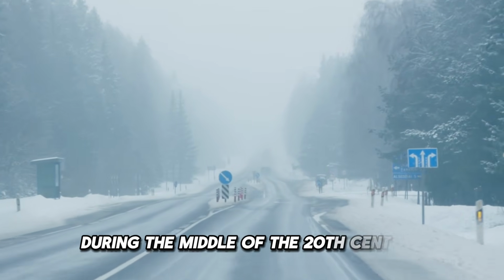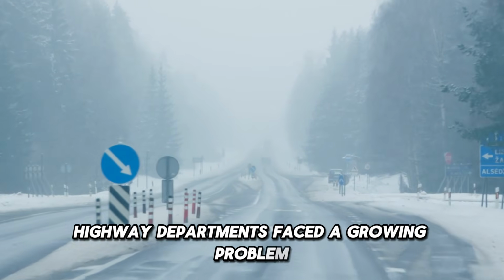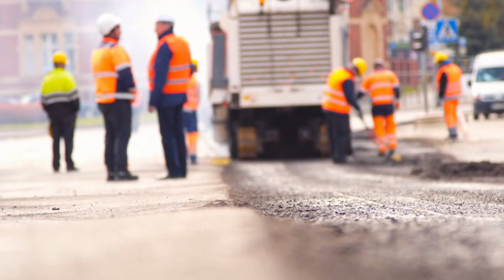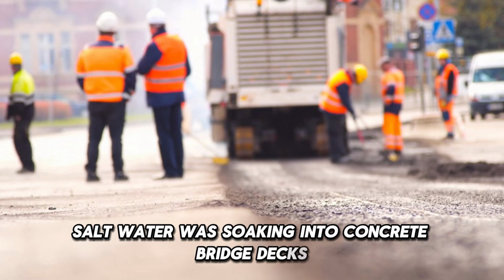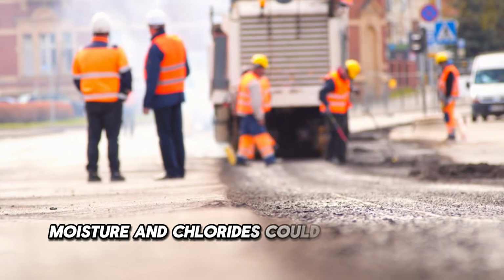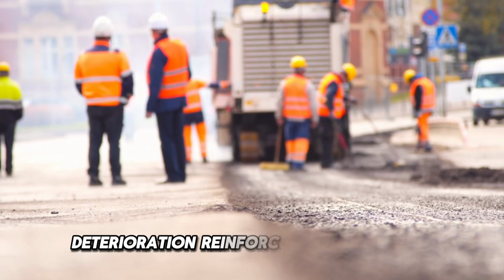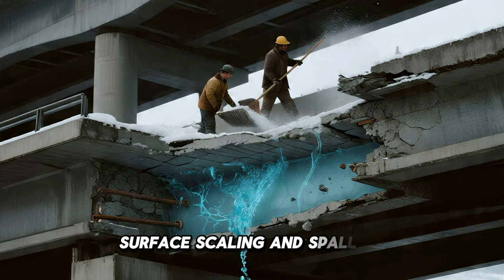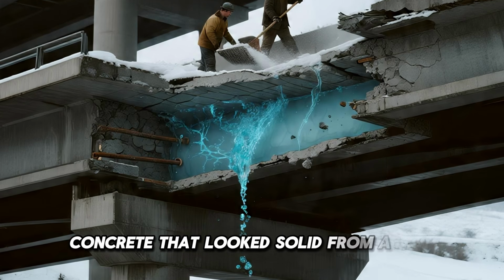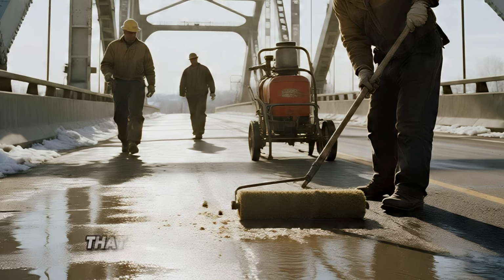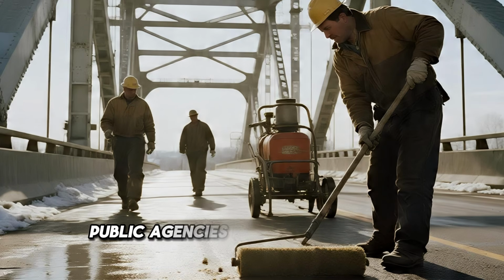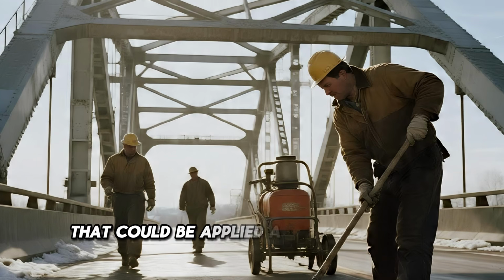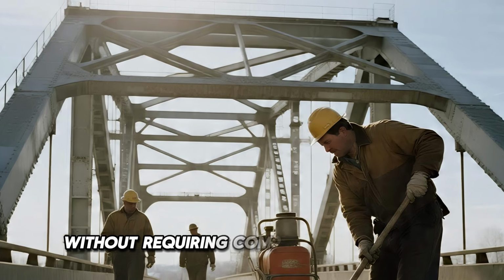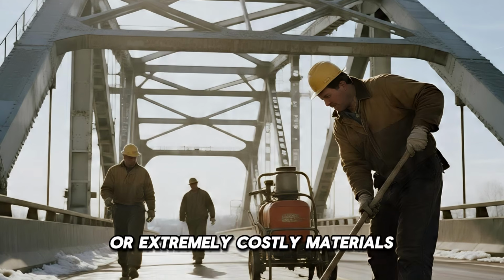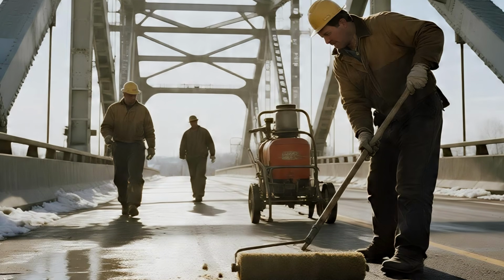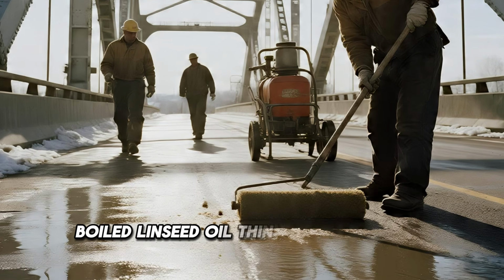During the middle of the 20th century, highway departments faced a growing problem as winter road salting became more common. Salt water was soaking into concrete bridge decks. Once inside, moisture and chlorides could contribute to freeze-thaw deterioration, reinforcement corrosion, surface scaling, and spalling. Concrete that looked solid from above could slowly begin breaking apart. That created an expensive challenge. Public agencies needed a protective treatment that could be applied across enormous areas of concrete without requiring complicated equipment or extremely costly materials. And one of the solutions they turned to was surprisingly familiar: boiled linseed oil thinned with mineral spirits.